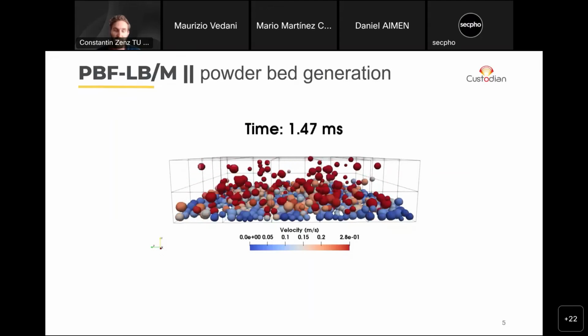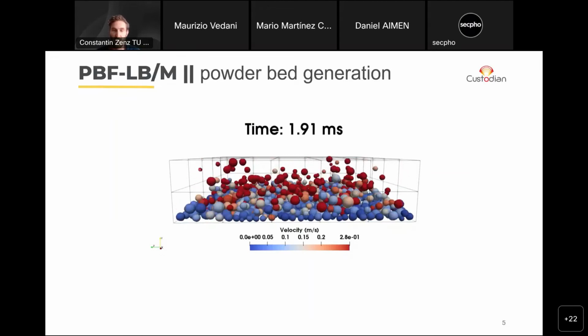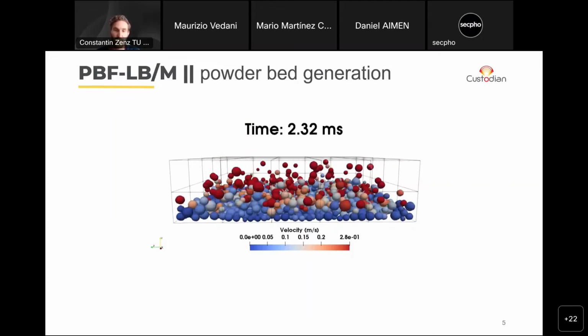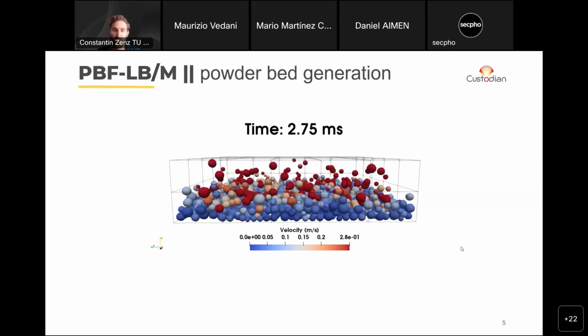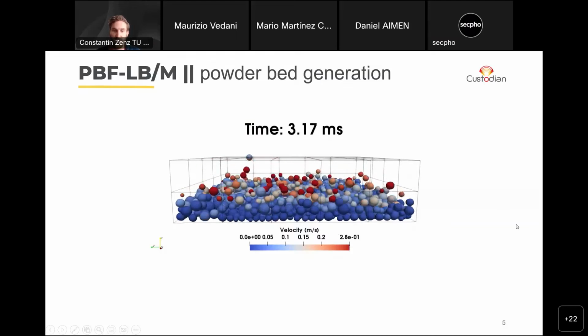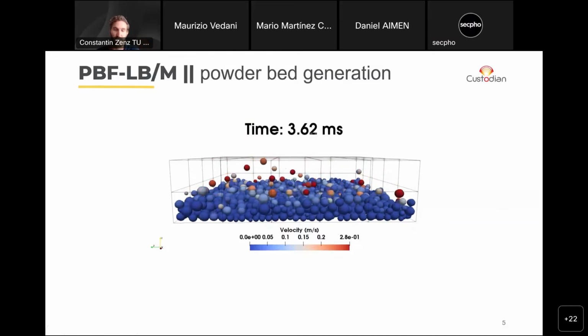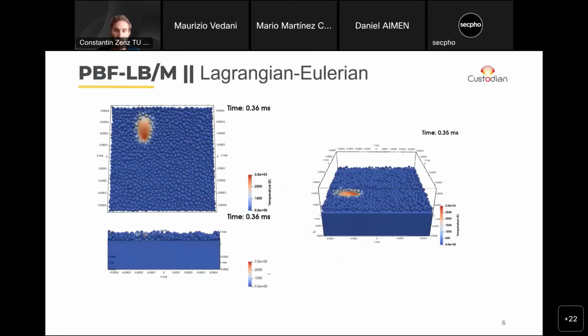Initially, we chose the approach of modeling individual powder particles. So here you can see a simulation where we try to achieve a realistic powder bed distribution of different sizes and so on by dropping powder particles so that we can accurately model the melting of the powder. And if we use such a powder bed in a simulation, you can see here now how this actually looks. The powder melts when the laser beam travels along and is added to the bulk material. And so layer by layer, we add material.